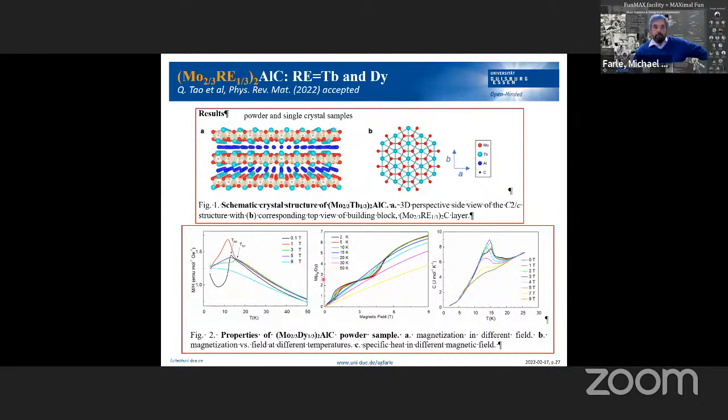When we look at the magnetization directly, this is the case for dysprosium, the magnetic moment of dysprosium evaluated from the magnetization curve, you see that as a function of magnetic field, the average dysprosium magnetic moment increases to the expected value only in large field. So that indicates there are non-collinearities in these rare earth materials.